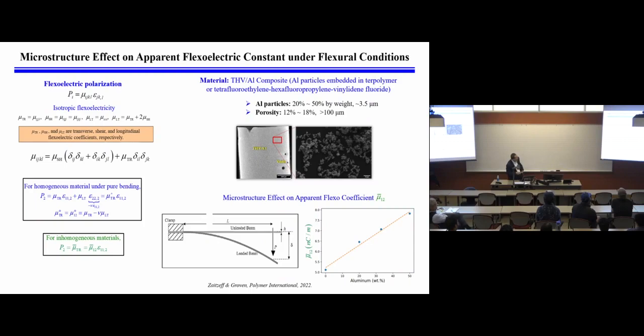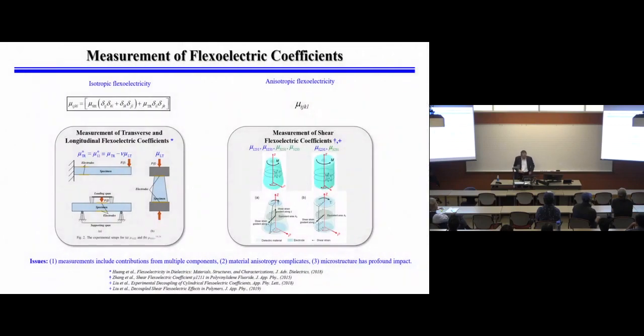I also want to mention that even for isotropic materials, you have three constants, the transverse, the shear, and the longitudinal. But the three are related through a relationship. So if you know any two, which is what I did here, then you can know the third. So I simplified it into this form. With that in mind, I wanted to see how microstructure influences this coefficient, which basically measures, per unit strain gradient, per unit bending, how much electrical output you're going to get through flexoelectricity.